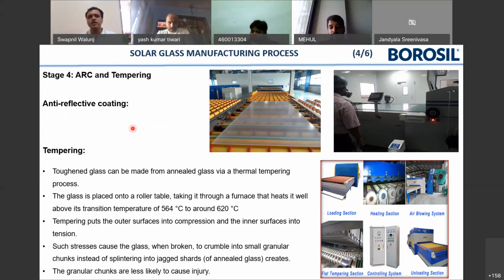Anti-reflective coating, as you know, is a coating of dielectric material that we impart on the surface of the glass, which minimizes the reflection, and ultimately the transmission is enhanced by 1.5 to 2.5%. That much higher yield you are able to get with these ARC coatings. I'll come to how we ensure that the best anti-reflective coating is applied later during the class. We use a very clean area for this. You can see in this picture the glass going inside the anti-reflective coating machine. Then the glass goes to a tempering section.